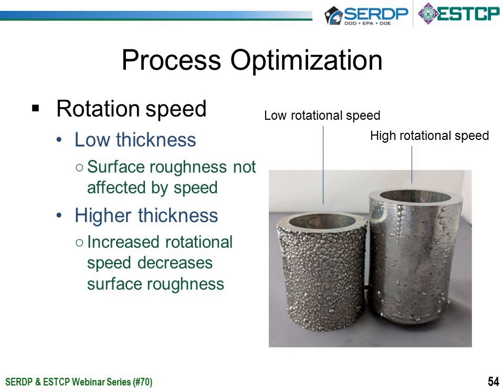Similarly, for rotation speed, slide number 54, at low thickness, the rotation speed didn't have a significant effect. But when we went to higher thicknesses, a low rotation speed also led to a lot of surface roughness. And you can see all the nodules in the image on the left, which is significantly reduced when the rotation speeds were increased.